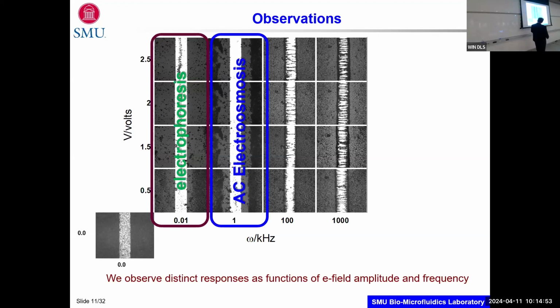Then you see a case where the particles are leaving these electrode gaps. That's actually a convective flow, called AC electroosmotic flow. It is quite effective if you happen to have a thick electrical double layer. If you go into high concentration buffers, it's going to get thin, and this effect is basically diminished. However, if you're using high conductivity buffers and large electric fields, there are Joule heating based effects, which induce electrothermal motion, which I'm not going to talk about in this talk.